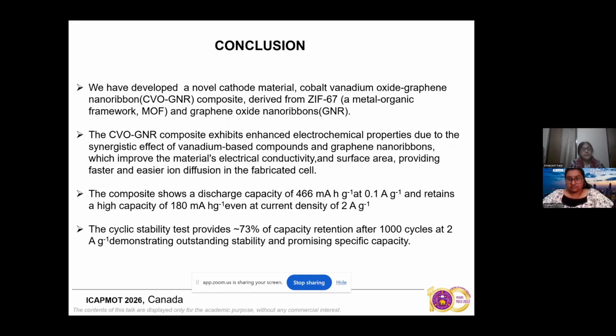So we have developed a novel cathode material, a cobalt vanadium oxide graphene nanoribbon composite derived from ZIF-67, a metal organic framework, and graphene oxide nanoribbons. This CVO-GNR composite exhibits enhanced electrochemical properties due to the synergistic effect of vanadium-based compounds and graphene nanoribbons, which improve the material's electrical conductivity and surface area, and provide faster and easier ion diffusion in the fabricated cell.